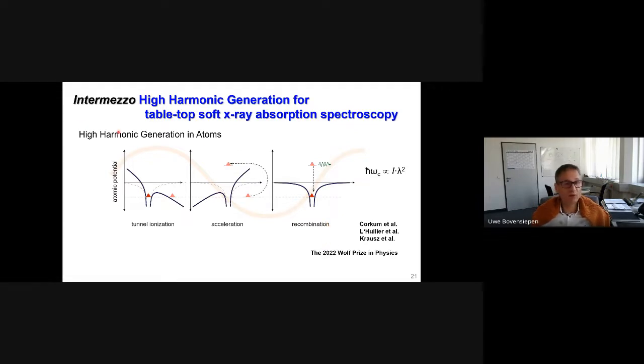And this is based on harmonic generation in atoms. Just as a reminder, you get this harmonic generation if you have laser fields, this is here this red line, that are large enough to tilt the atomic potential. And then you have initially here this tunnel ionization where the electron tunnels out of the atom. Then this free electron is accelerated in the laser field and first taken away and put back onto the core where you find a recombination. And this was pioneered by Paul Corkum, Anne L'Huillier, and Ferenc Krausz, and for their work they got this year the Wolf Prize in Physics. And we explored this further.